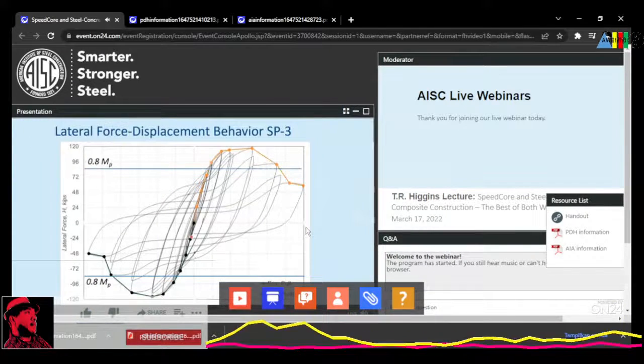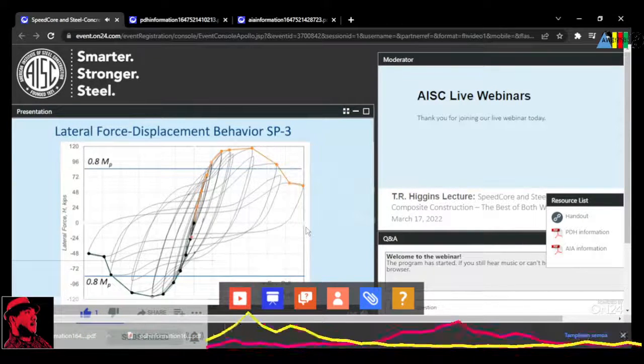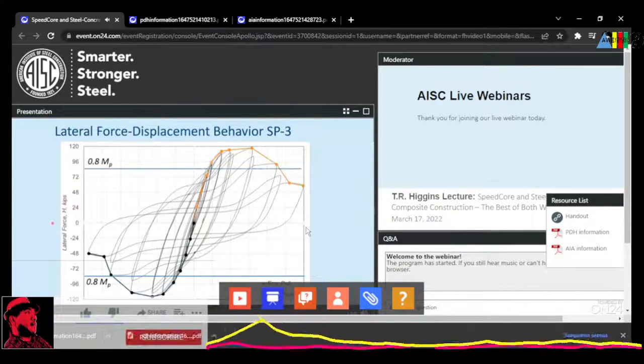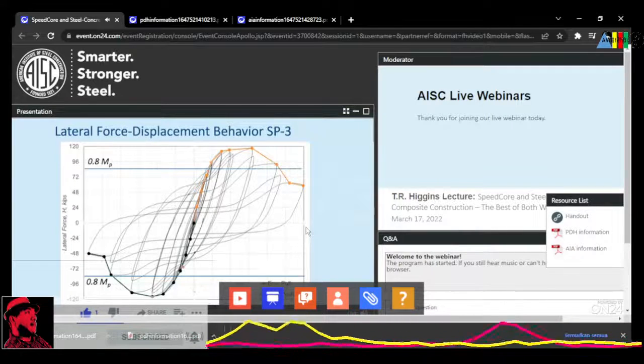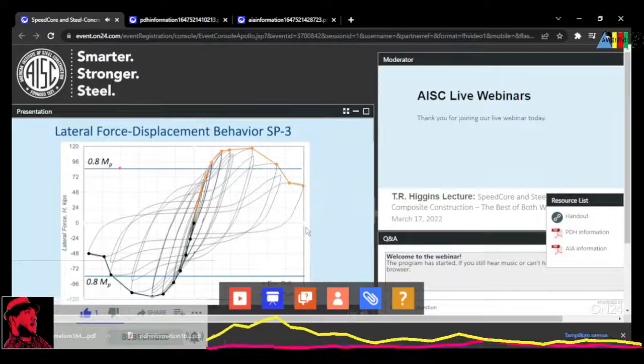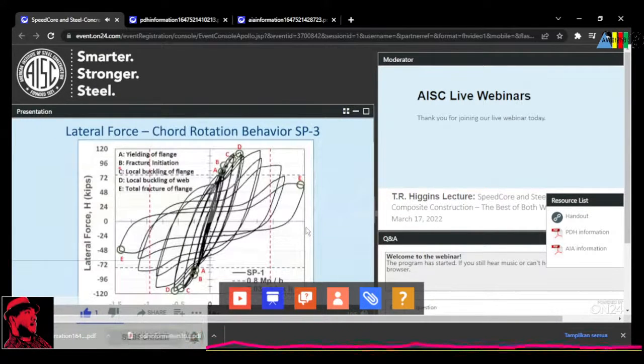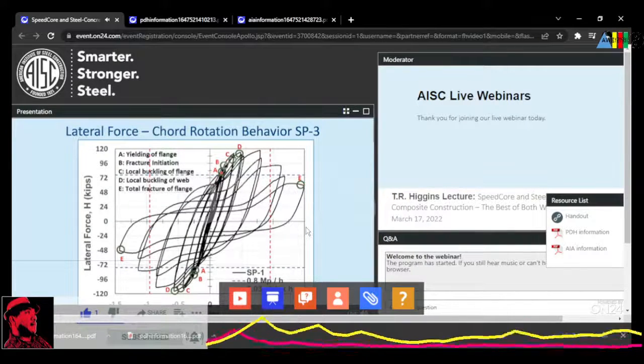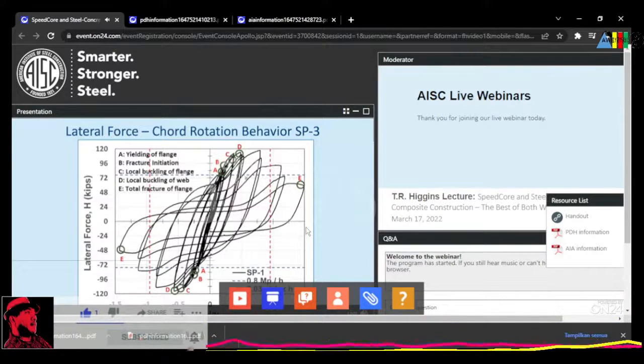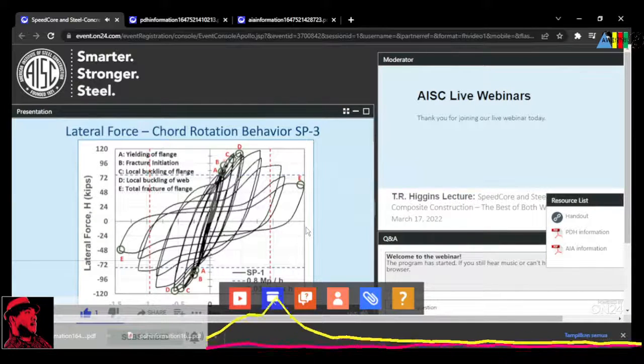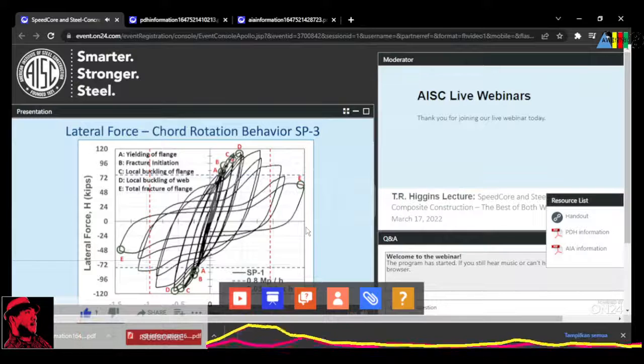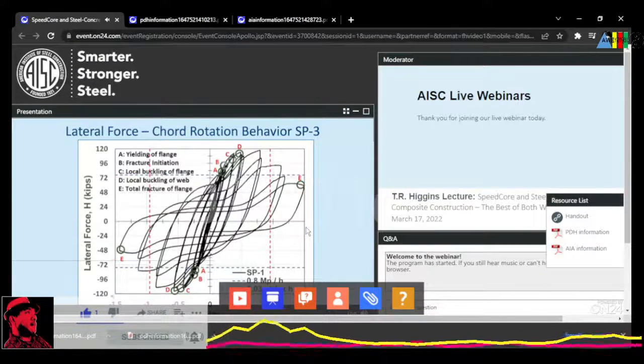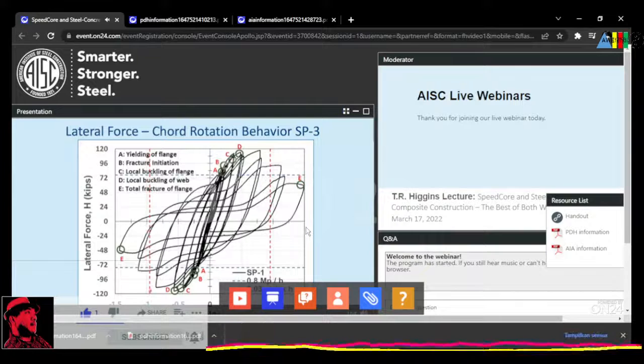This is the lateral force displacement behavior of the specimen subjected to the ATC 24 loading protocol. You're seeing the lateral force versus beam end displacement response. The backbone curve has been identified, and 80% of Mp horizontal lines have also been shown. This is showing the complete response along with the occurrence of various events A through E. A corresponds to yielding of the flange, B corresponds to initiation of fracture, C corresponds to initiation of local buckling of the flanges, local buckling of the webs, and then eventually total fracture of the flange as well. Horizontal lines corresponding to 0.8 Mp are indicated in blue, and vertical lines corresponding to a rotation capacity of 0.03 radians are also identified here.